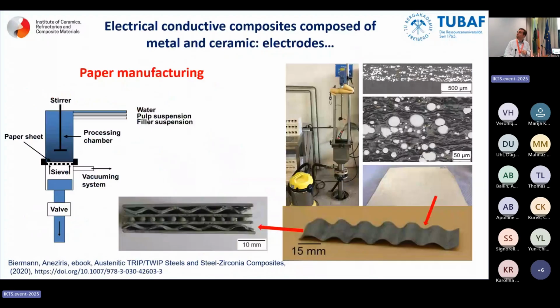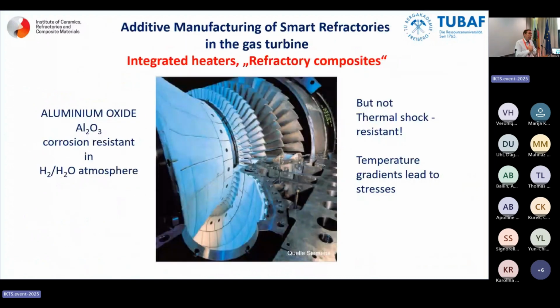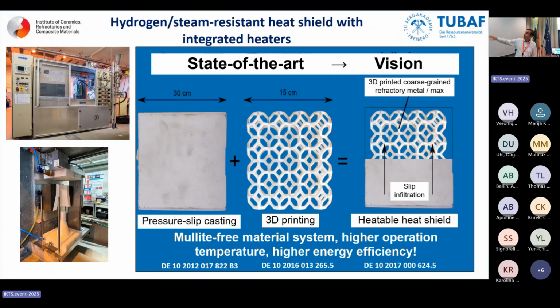And somebody would say, why are you doing these issues? Yes, because if you have a gas turbine, who have worked a lot of years with the guys, yes, you have the heat shields. Yes, these are aluminum mullite systems. It works up to 1300 degrees in case of normal combustion. But if you go to H2 combustion, you have problems. So you have to get the mullite outside, or you have a heat shield as we do it with a pressure slip caster, and you integrate a 3D heating element. Then you don't have the thermal shock problem, and you can increase the application of the gas turbine. And this is a Carnot gas turbine. It means the higher the temperature, you get a positive impact according to the efficiency.